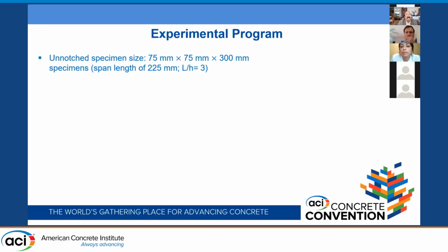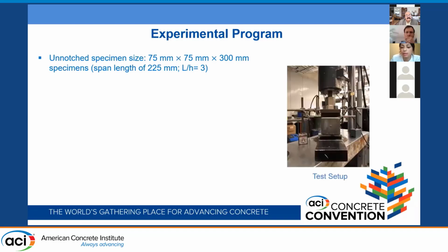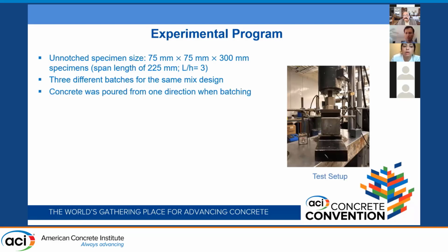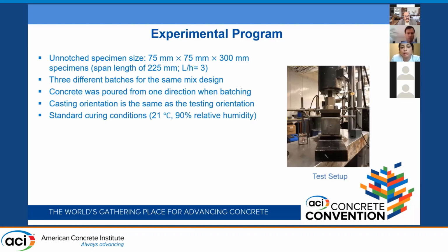Now, as for the experimental program, in here we tested unnotched specimens of the size of 75 by 75 by 300, as you can see here, and we used 2 LVDTs, one at each side. We used 3 different batches, but they all were for the same mix design. Concrete was put from one direction, casting orientation was the same as the testing orientation, curing was standard curing.